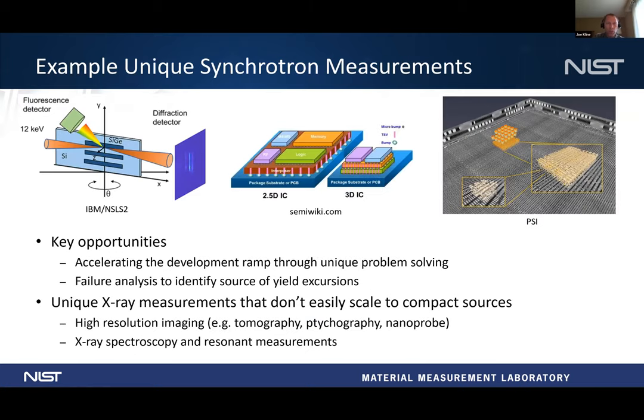And so just to finish up, I wanted to discuss a little bit some of the unique synchrotron measurements that can be done and how that applies back to the semiconductor industry. This is stuff not that my group has done, but that other people have done, and I'm relaying a lot of what we've learned from meetings we've had with the semiconductor industry and what their needs are, where X-rays can help them out. In particular, the first thing on here is an example with IBM and NSLS-II, where they're looking at silicon germanium nanosheet structures. In this particular case, they could use a nanoprobe to do diffraction and fluorescence on the silicon germanium multilayers in the nanosheet to be able to map out the local strain.